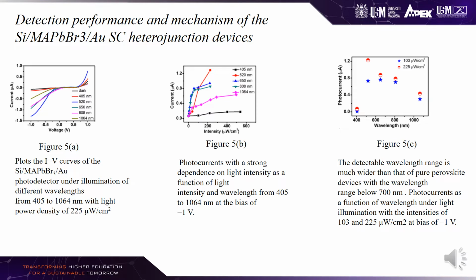And figure 5c shows that the detectable wavelength range is much wider than that of pure perovskite devices with the wavelength range below 700 nanometers. Photocurrents as a function of wavelength under light illumination with the intensities of 103 and 225 microwatt per centimeter square at bias of negative 1 volt.